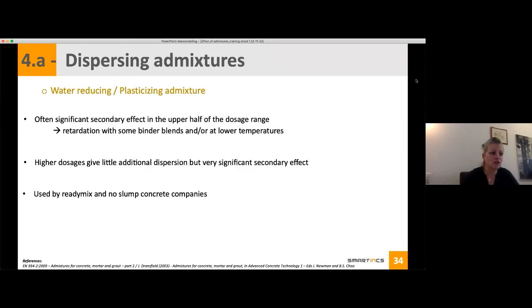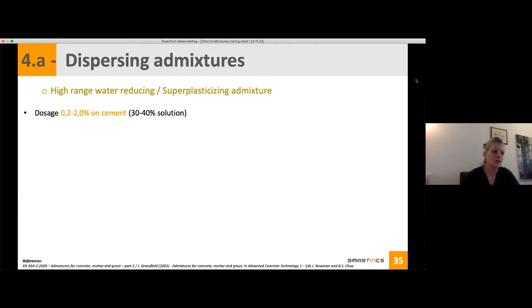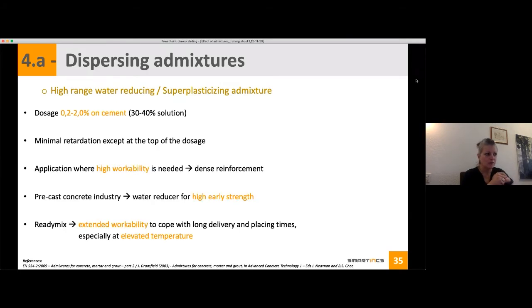They are used a lot in ready mix concrete companies. Now, if we look at the high range water reducing and superplasticizing admixture, the dosage is a bit higher than what we've seen for the plasticizing admixture, 0.2 to 2% on weight of the cement. A positive about this admixture is that it has minimal retardation, unless you really go to very high dosage. This also means that the application is much wider, where you really need a high workability.